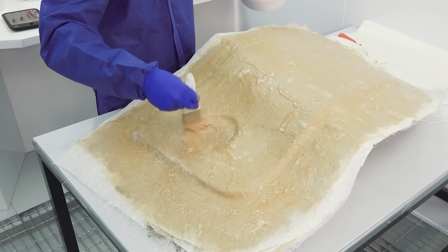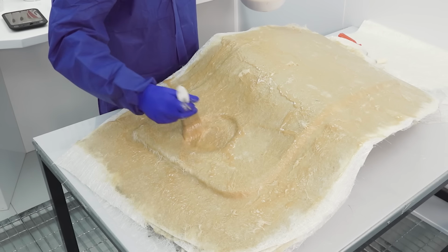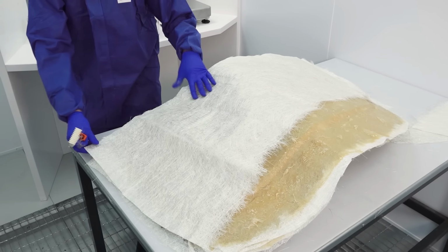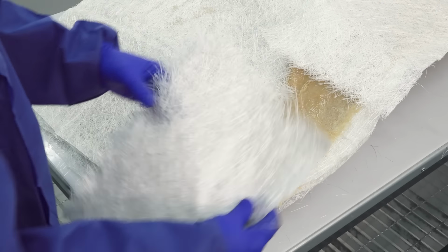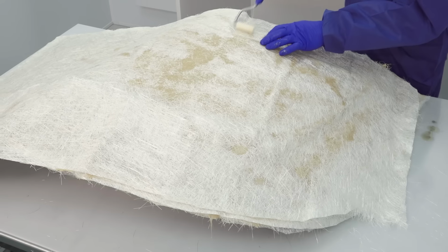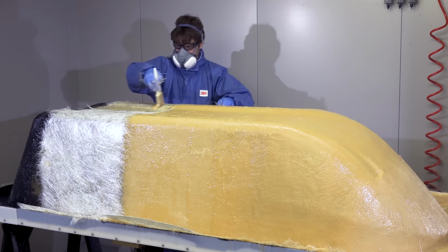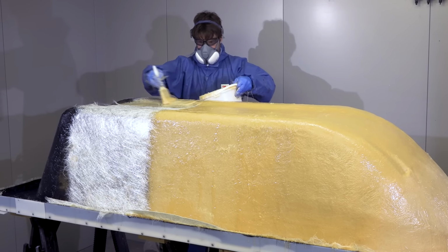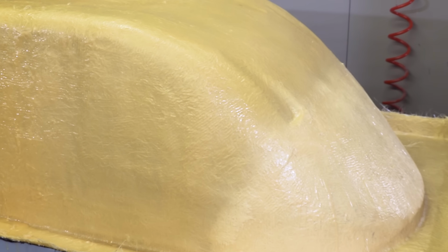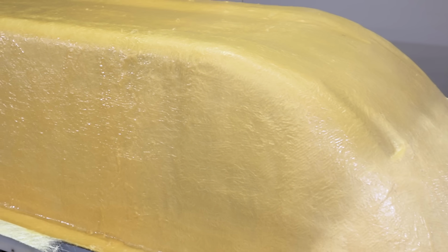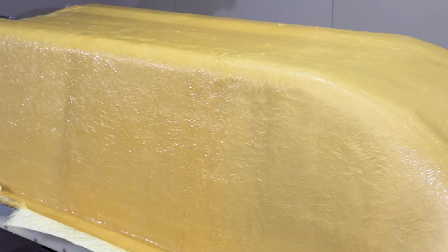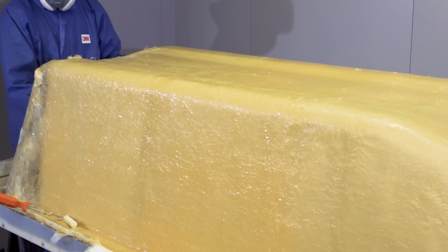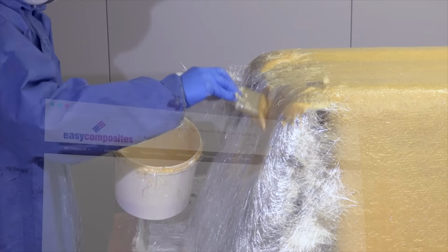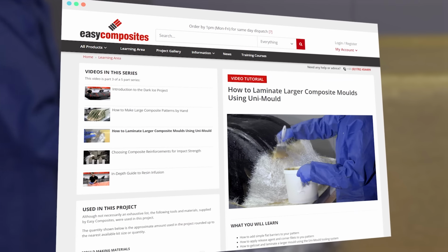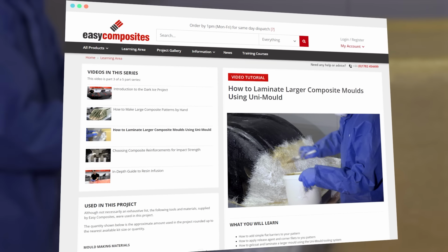If your mould is larger than 1 square metre, then it's unlikely that you'll have enough time to properly wet out and consolidate all 4 layers with one batch of resin. So what you should do in this case is laminate the mould in strips of approximately half a square metre at a time with all 4 plies, then mix a new batch of resin and continue to work your way down so that the cure will follow you as you work your way along. Have a look at the video where we make a mould for an expedition sledge to see this technique in action.